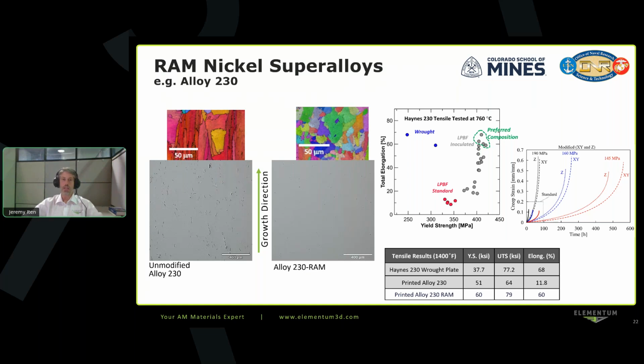But the gray is looking at our development that we did, funded by the Office of Naval Research, together with the Colorado School of Mines. We looked at a wide range of different RAM type and inoculated type compositions. Those dots, the scatter you see, is because those are all representing different compositions, different process parameters, and so on. But if you look at the preferred compositions in the top in that green circled area, those are the type of performance you expect now with the most favorable preferred composition that we've selected for our product.